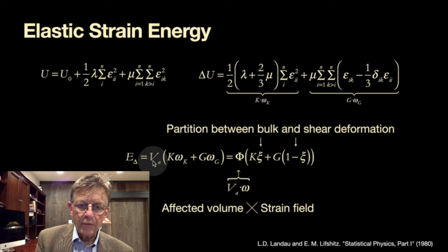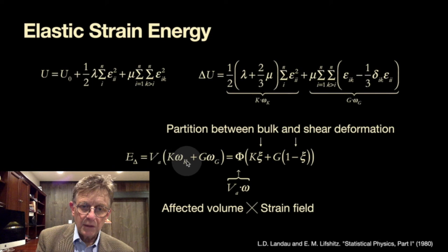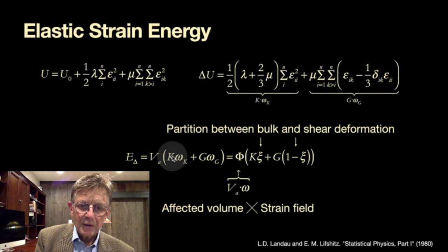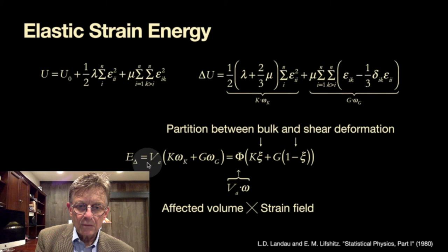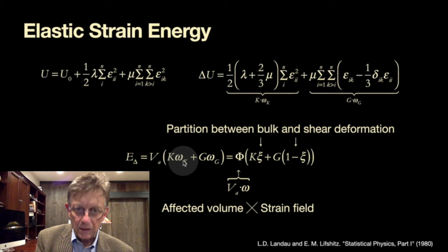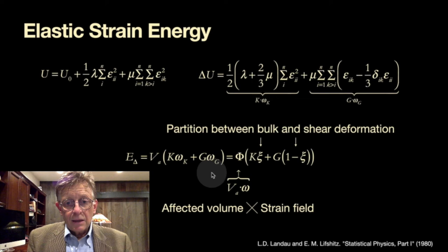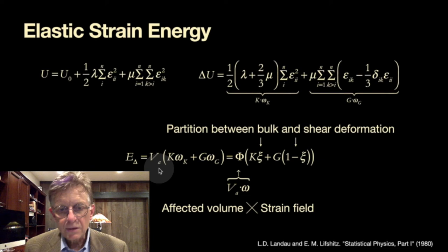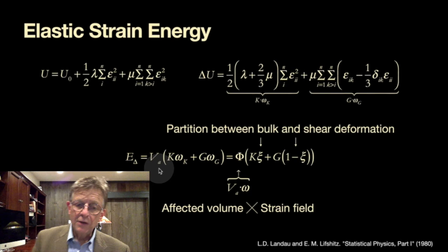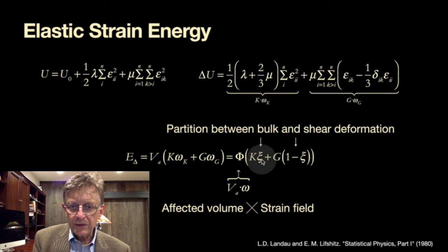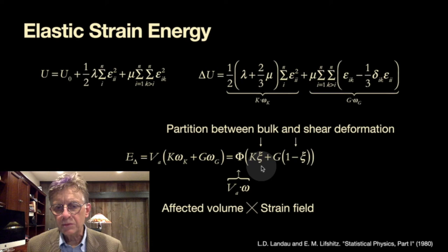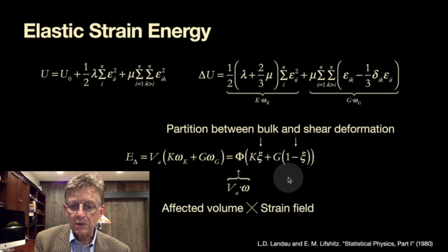We can rewrite this, subtracting U0 from both sides and then get this term lambda plus two thirds times mu which ends up being the same as the bulk modulus. Then mu itself is the shear modulus. The effect of strains in the diagonal will be isotropic deformations and these will be all the shear deformations. We lump into a factor omega K and omega G referencing the effect of strain deformation. We don't know what that is exactly but we have an estimate which comes from the Debye-Waller factor, it means that the average thermal vibrational amplitude of atoms educates us on how much strain we can expect. So we regroup this and get for the activation energy the strain part of it, this term of this volume V affected which now has to multiply omega to become an energy. Or times K will be an energy so we need to multiply this with a volume, both the strain for isotropic deformation and the strain for shear deformation and get this factor and call this volume the affected volume.